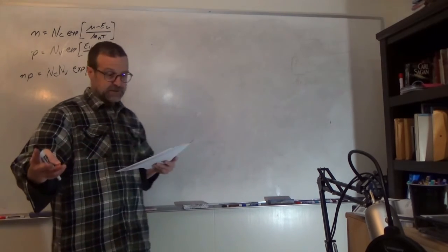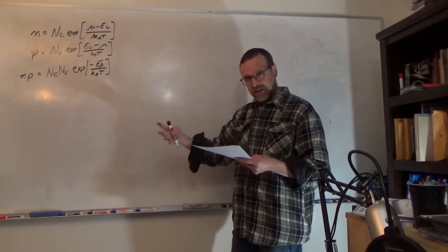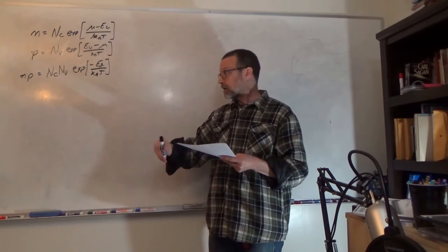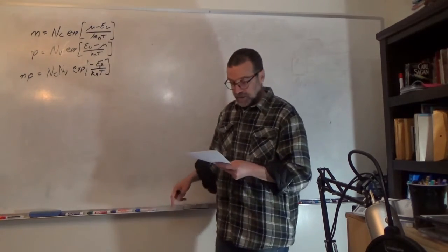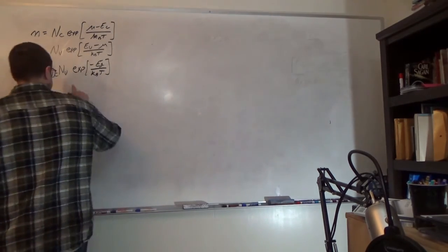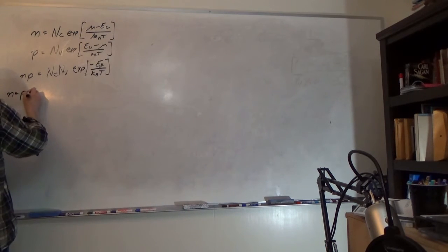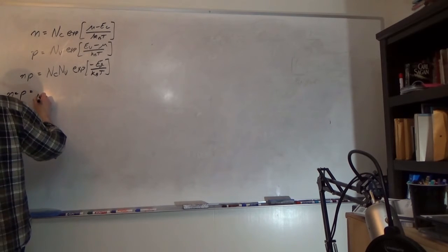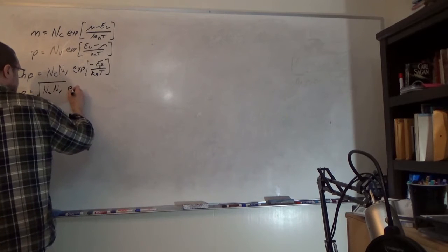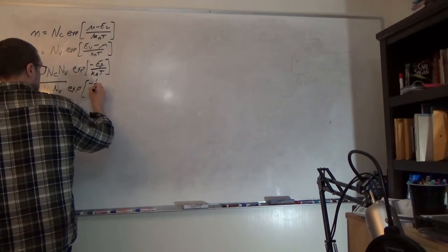If we're dealing with an intrinsic semiconductor — not thinking about dopants contributing to the charge carriers — then n and p have to be equal. From n and p, something interesting we can do is give them each equal shares of the product. So we can say n = p = sqrt(N_C · N_V) · exp(−E_g / 2k_BT).